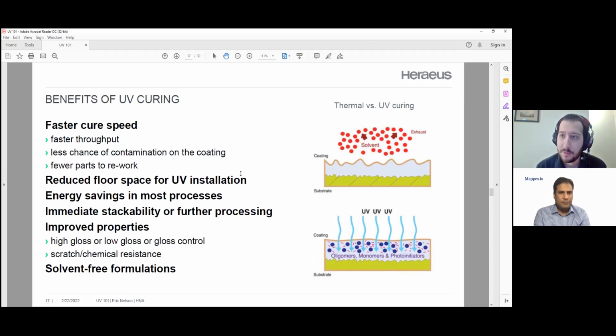UV is also stackable. So if a UV process isn't occurring fast enough, you can simply take a second lamp and add it to the process, and you can increase the speed, increase the throughput, and improve the efficiency that way. You can achieve certain properties that you wouldn't be able to achieve with a traditional paint or coating. The UV polymerization reaction is instantaneous and it's able to penetrate deep into materials.